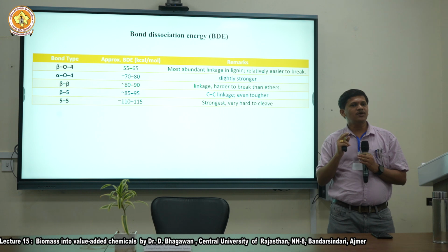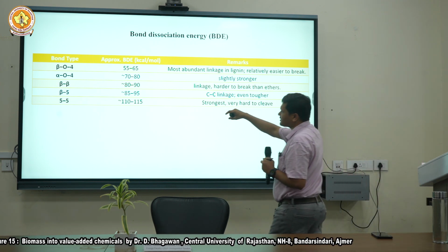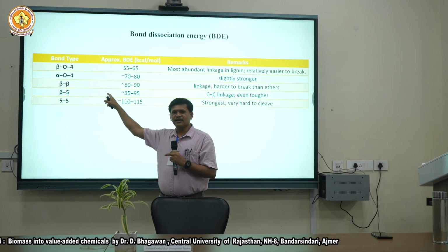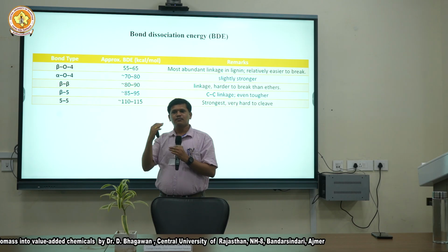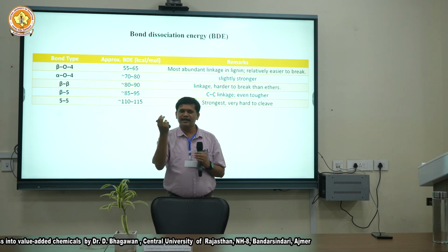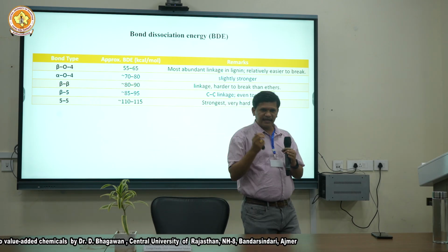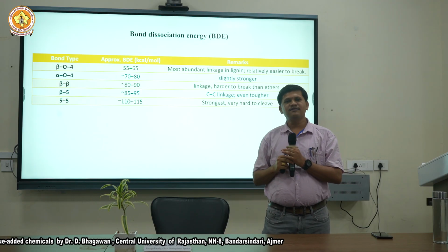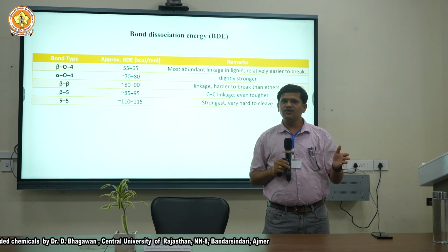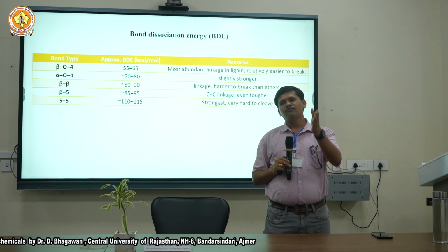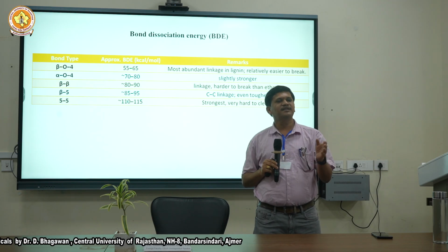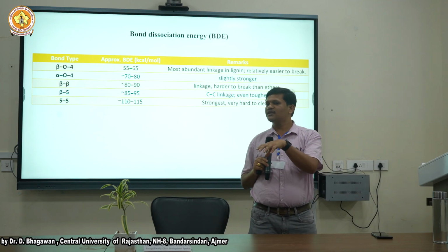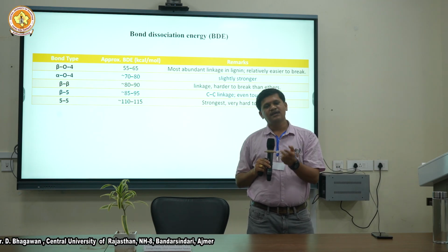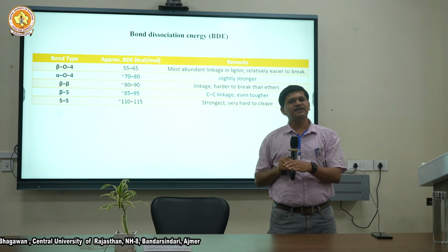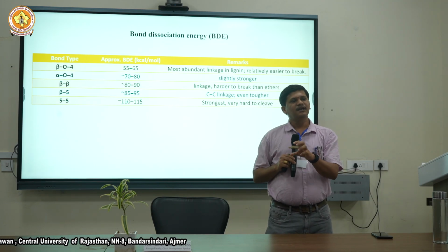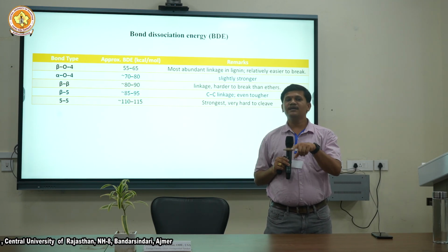And will it be possible to break down only this linkage beta O4, because this is not in the pure form. Whenever we extract lignin from the agriculture waste, first we will go for separation of cellulose by acid digestion, followed by alkali digestion. We will separate the lignin, and whichever remaining portion retains with the solid phase, that again goes for acidification, and further it will become a pure lignin compound.